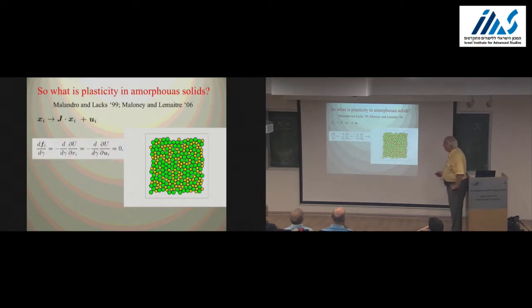Let me start with the fact that I have a force F_i on every particle that is zero before and after. So I made a change that I parameterized by gamma. This affine transformation will be parameterized by some gamma, for example, in simple shear, just the strain. And we know that dF_i/dgamma is zero. It was zero before, it was zero after. But the force F_i is nothing but minus the derivative of the energy of all the particles with respect to R_i. Okay, so that's the force. And this is the d gamma. So I have now a strange double derivative, one partial and one full.